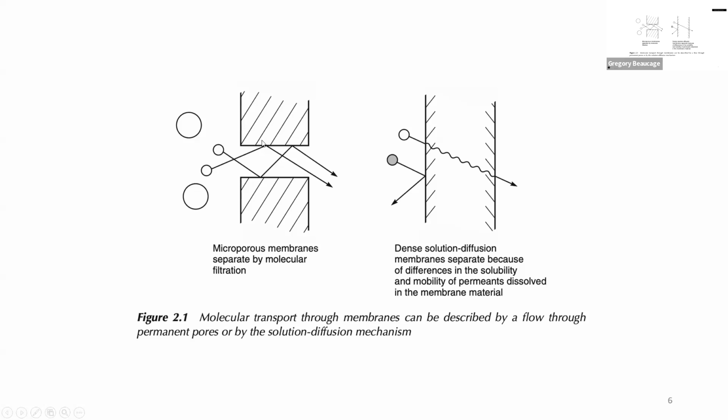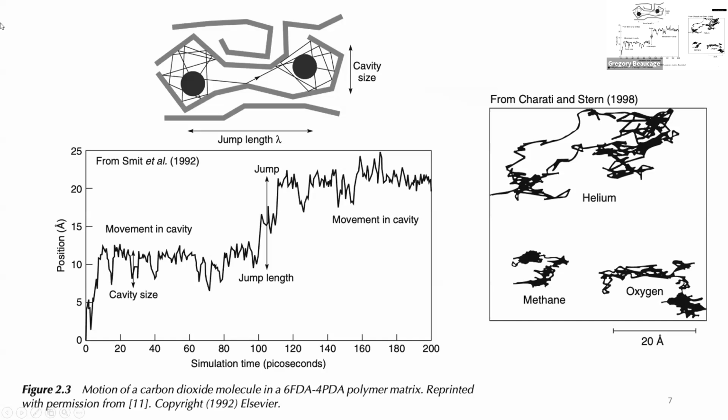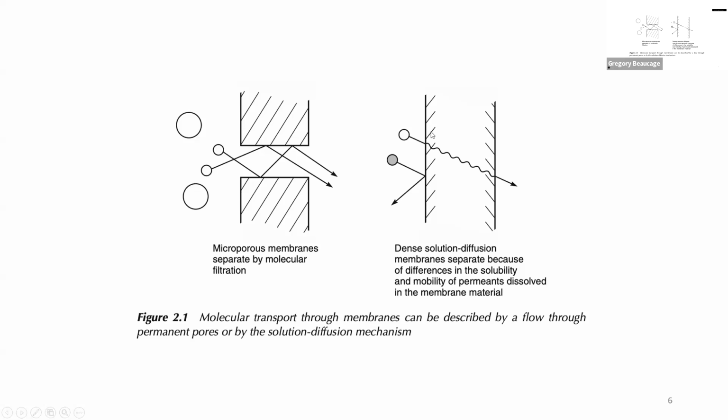This is showing the difference: this is a diffusion path through them. This is absolutely diffusion, and this is not. And this is showing that if you can't absorb it, then you can't diffuse it. So if you're doing a separation where it's soluble in one, not the other, you're going to get a good separation. So it isn't this idea of squiggling through. Diffusion is the idea that it's moving through at such a slow rate that it's exploring the entire universe in here. So it can move in any direction once it's in here.